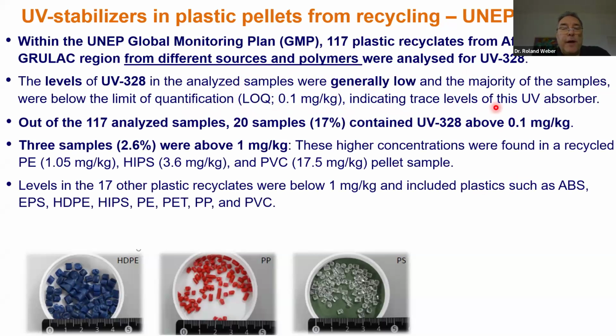So in total, we have detected 20 samples above 0.1 milligram per kilogram, that's 17%. So 3 of these samples, this means 2.6%, were above 1 milligram per kilogram. These higher concentrations were found in a recyclate of a polyethylene, had 1.05 milligram per kilogram, then HIPS with 3.6 milligram per kilogram, and a PVC sample with 17.5 milligram per kilogram, pellet samples. And the levels of the other 17 were somewhere between 0.1 and 1 milligram, and these were plastics included ABS, EPS, high-density polyethylene, another HIPS, another polyethylene, a PET, a polypropylene, and a PVC.